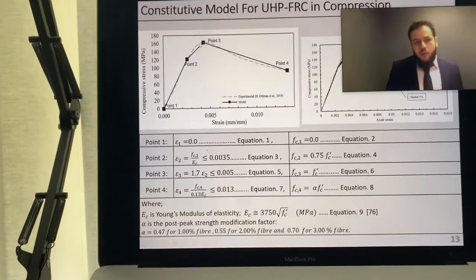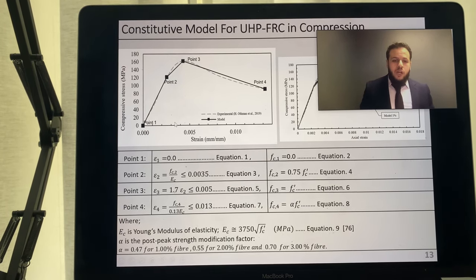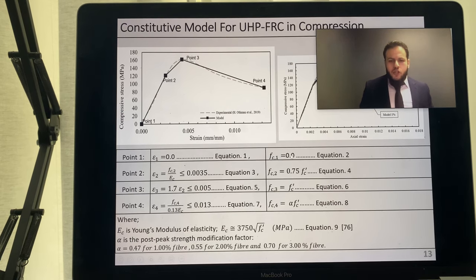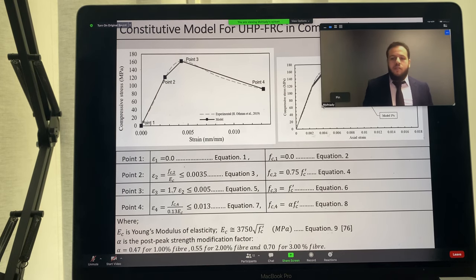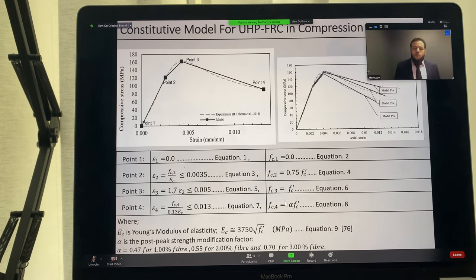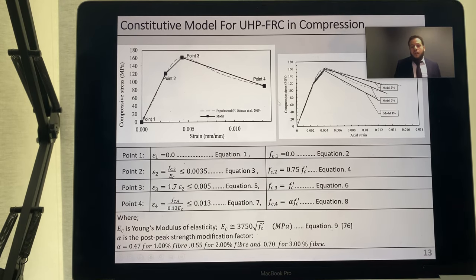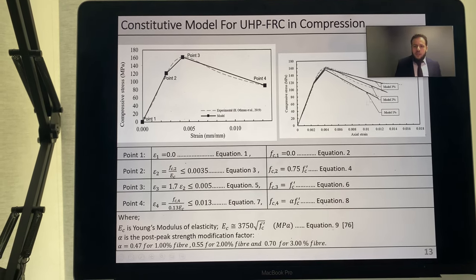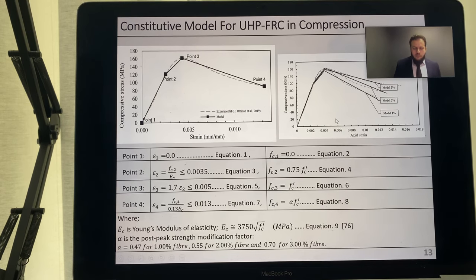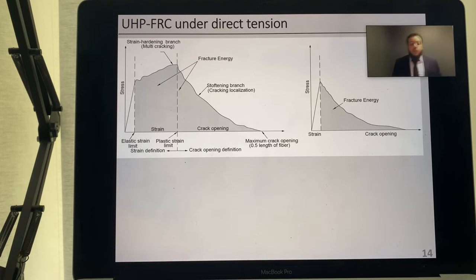Using the FIT approach, I marked points of apparent change in slope in the stress-strain curve and developed relationships that limit the ultimate strain to 0.013, although some specimens reach higher strains. The effect of fiber is accounted for using a factor alpha. I applied the model to the other two fiber contents from this study and it had good results compared to experimental data.